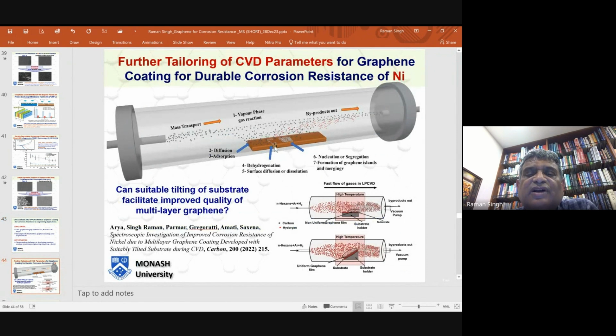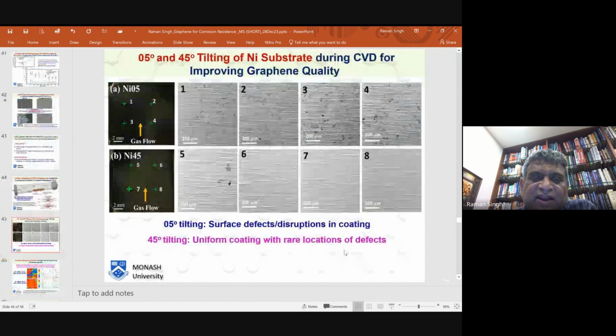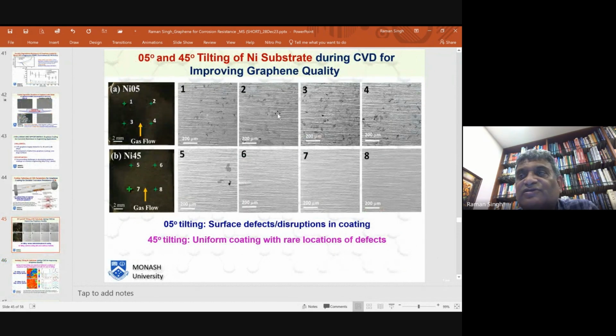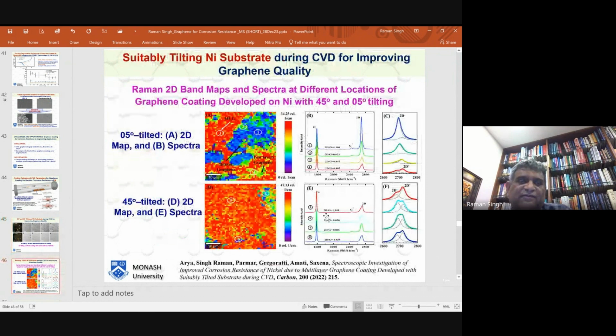Earlier, we used to have flat samples in the CVD chamber. We tilted the sample by 45 degrees, and I will show you the advantages. This is 5-degree tilted, which is almost like flat, and you can see there are lots of defects in the graphene that you develop. But if you have 45-degree tilting, you can see that the surface is almost free of any defect. So that tilting was very helpful.